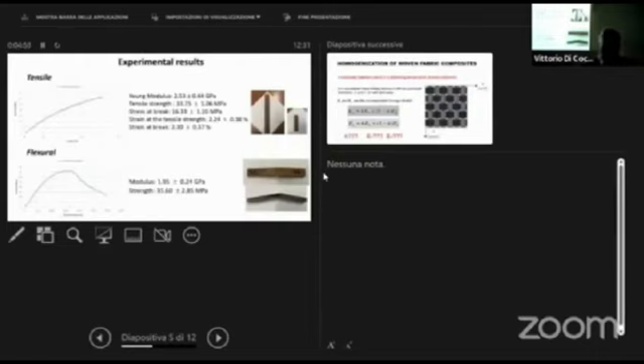So these are the experimental results. The tensile tests and flexural tests, as I said before, we processed the stress strain curves in order to obtain some parameters, but I want to focus the attention on the modulus because we have determined this modulus also using a very simple theoretical approach, and we see that in this case, in tensile tests, we have a Young modulus of 2.5 gigapascal that is very similar to the tensile modulus of the matrix, while